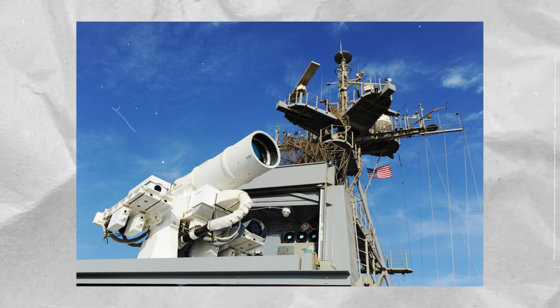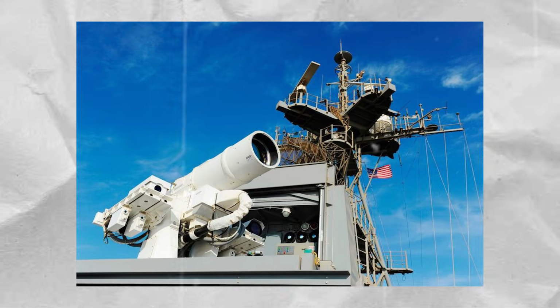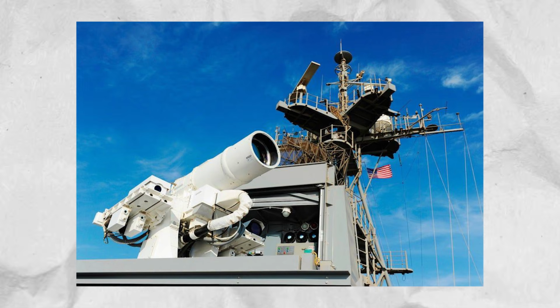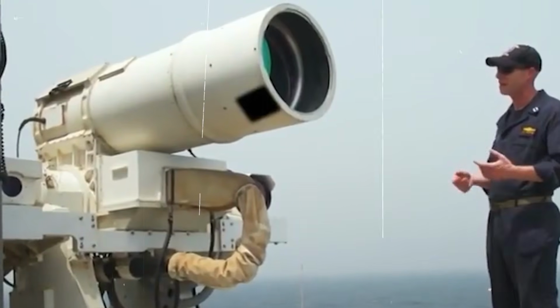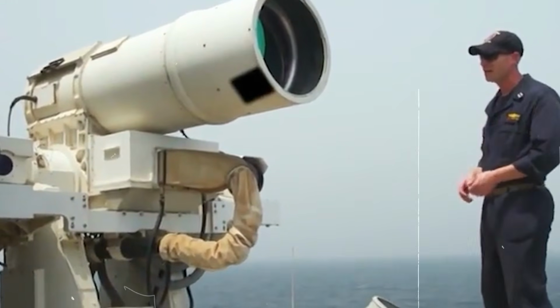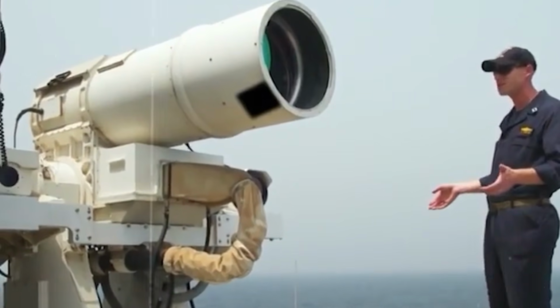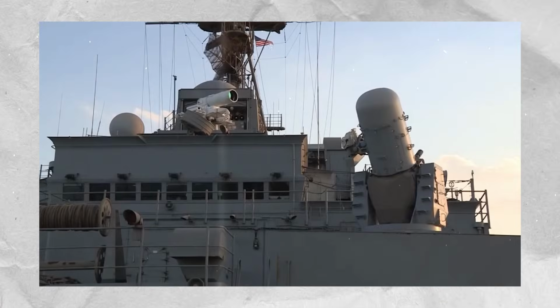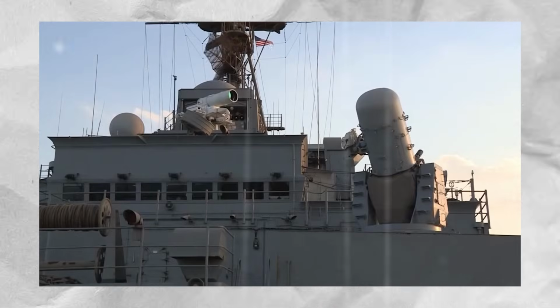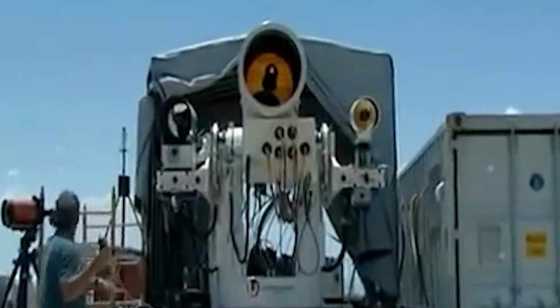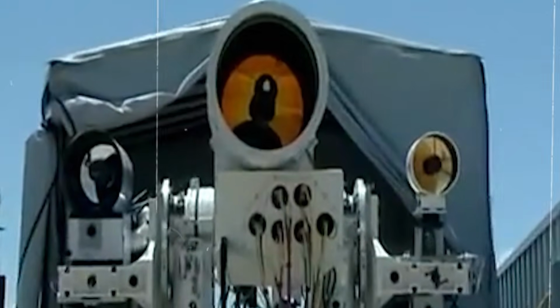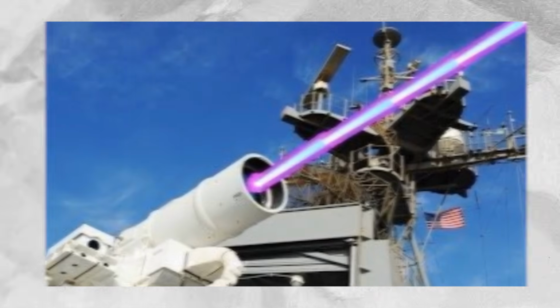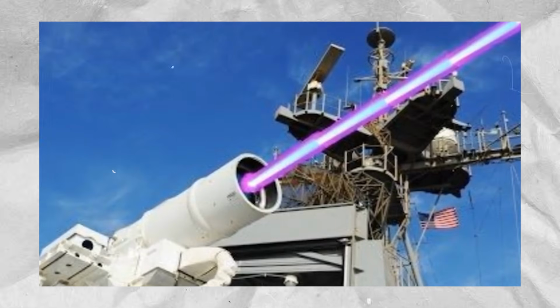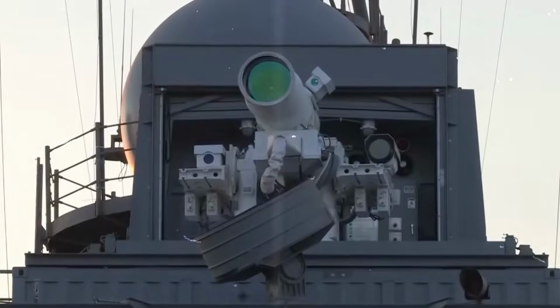At 1 kilometer, the difference between a coherent and an incoherent 30 kilowatt source is the difference between a spot approximately 10 centimeters across, close to the diameter of a large coin, and an illuminated area spread across several square meters of target surface. Power density measured in watts per square centimeter is what causes thermal damage. The 10 centimeter coherent spot at 30 kilowatts produces approximately 380 watts per square centimeter, enough to bring carbon fiber composite to structural failure temperature in 2 to 5 seconds, depending on layup and thickness.